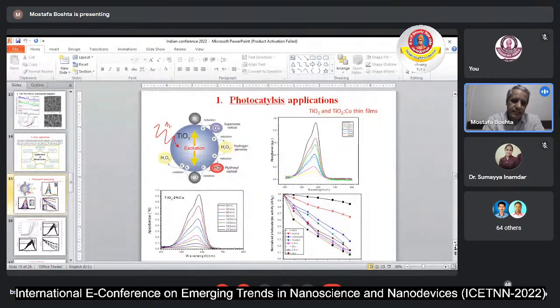form of thin layer. Most of the people in this area use the titanium oxide in the powder form, which is not easy to collect again from the solution and from the chemicals. But a thin layer is easy to add to the solution and also to remove from the solution, which makes it a simple way for the photocatalytic. So that's one of the advantages of the thin layer of the material used in the photocatalytic area.